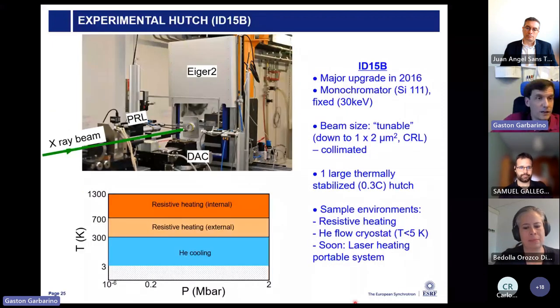ID15B was upgraded in 2016. We are working at a fixed energy of 30 kiloelectron volts, and we can focus the beam down to 1 by 2 microns in the vertical and horizontal directions. And this is what we can see here: at the position where the green line finishes, the X-ray beam is focused, and that is where our diamond anvil cell will be placed.